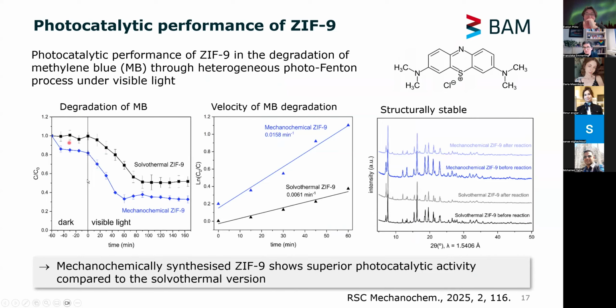And you can see here that the degradation, so our mechanochemically derived ZIF-9 performs better and has a higher velocity in the methylene blue degradation as compared to the solvothermal counterpart. And this has to do, of course, with the fact that we have this different morphology, and also we have intrinsic effects that are derived throughout the mechanochemical process, but they are then beneficial when we think about application in catalysis. The structure stays stable in both cases, which is also a plus for cyclic processes.